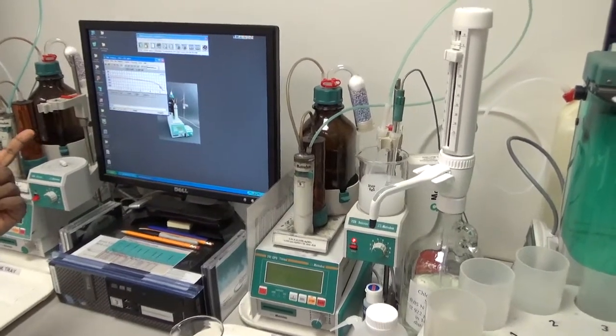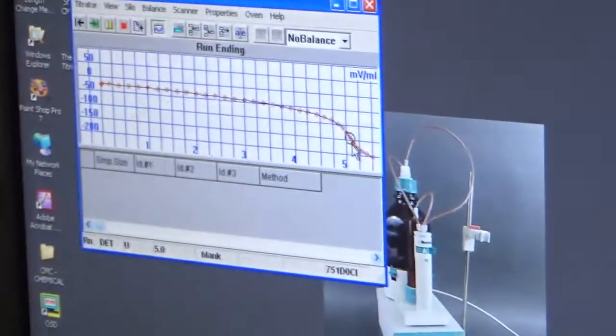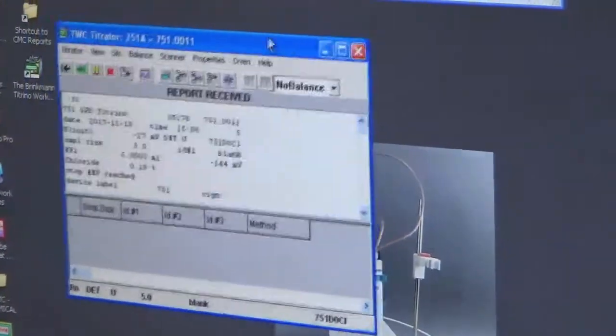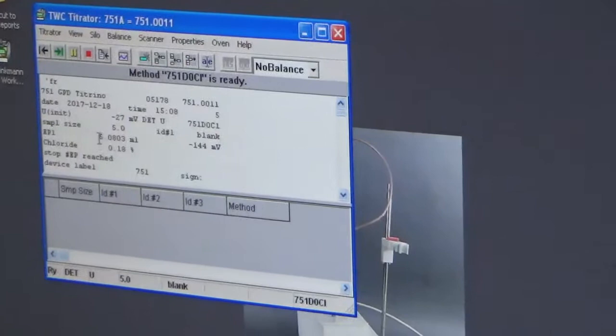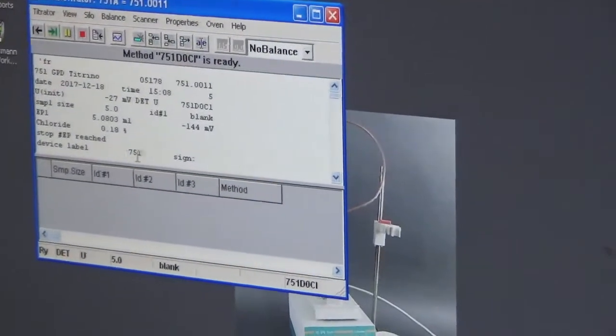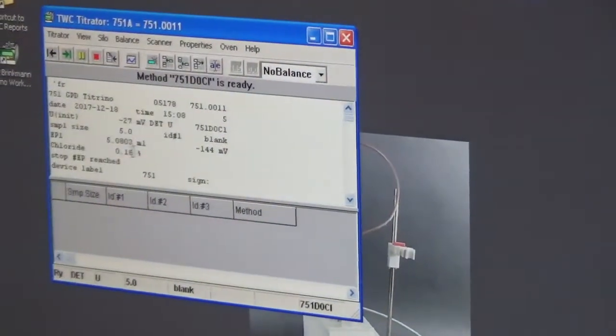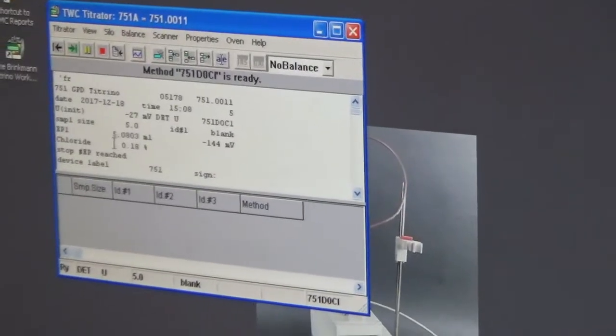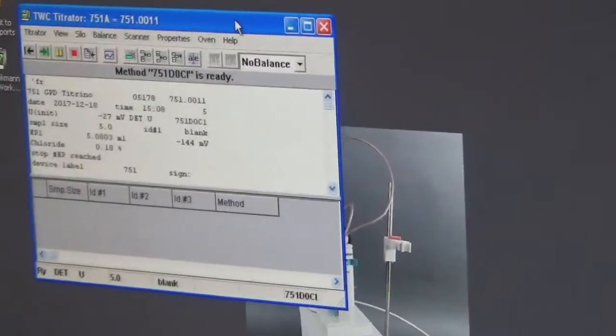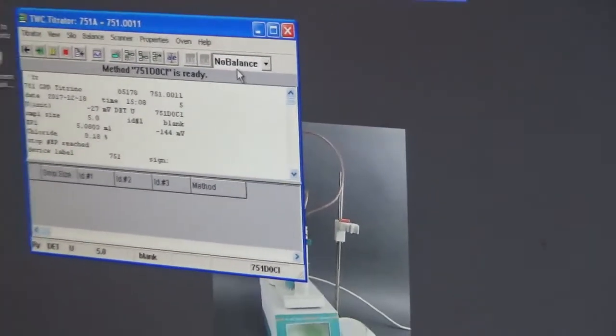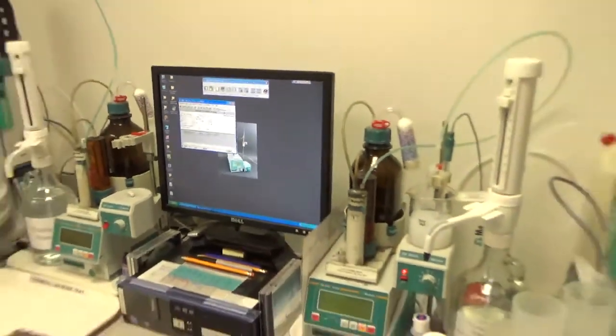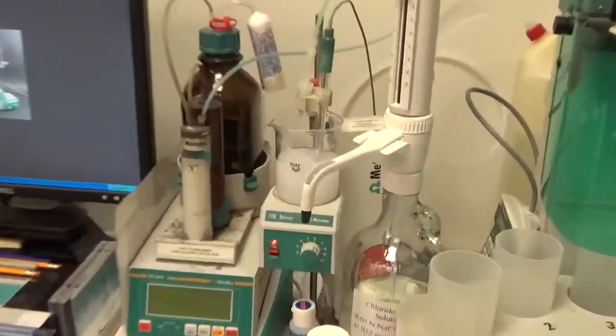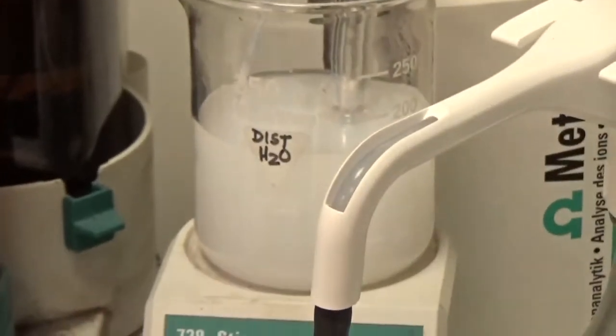Here the equivalence point is found, somewhere near 5, since I added 5 milliliter sodium chloride. It was found at exactly 5.08 milliliter, which corresponds to 0.18% chloride in that solution. From silver chloride, the color turns to milky white color from the silver chloride precipitate.